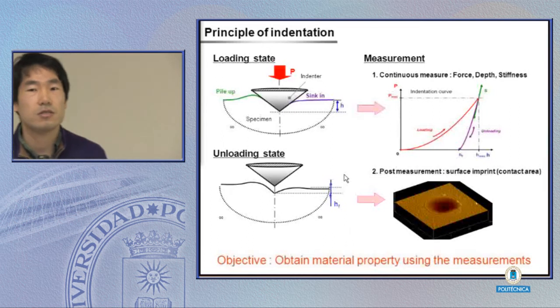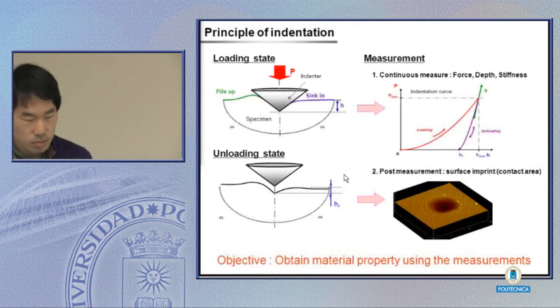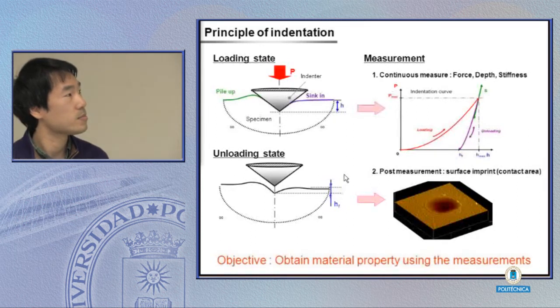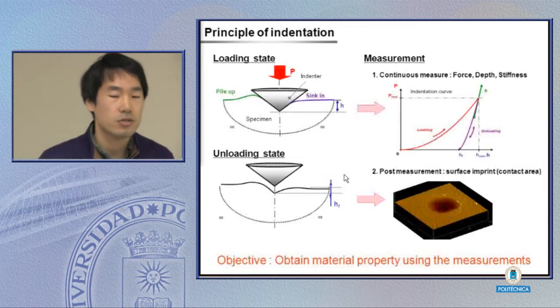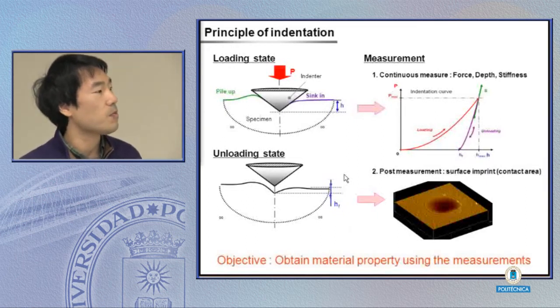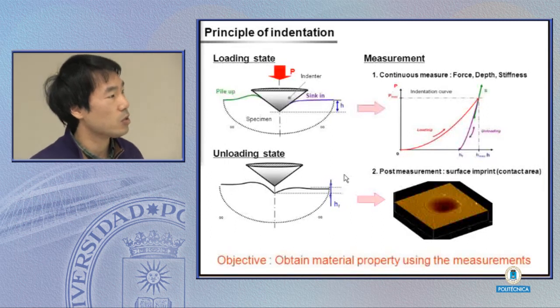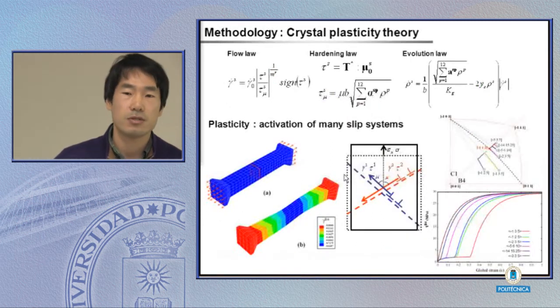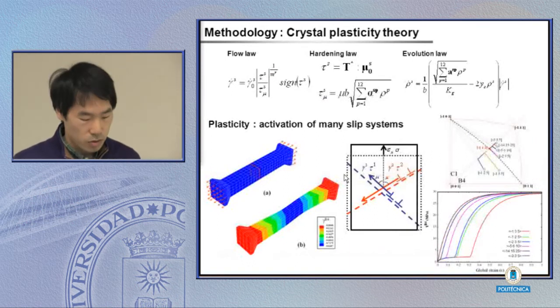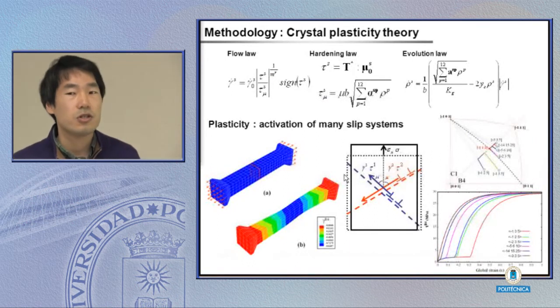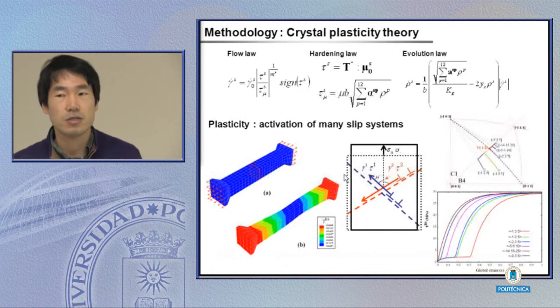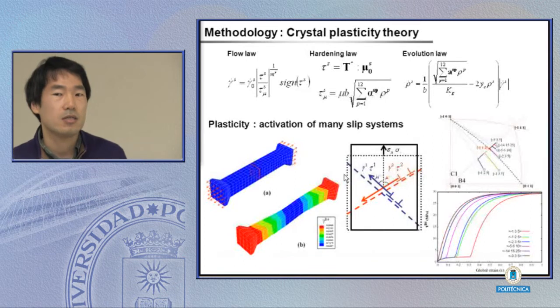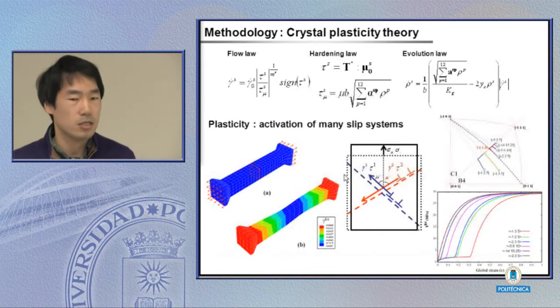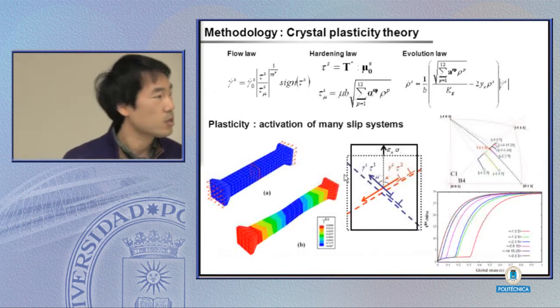Now, let's scale down to the microscale simulation, such as nano-indentation. The objective of nano-indentation is to get the material properties using the load displacement curve and surface imprint. So this nano-indentation procedure can be simulated by FEM simulation or crystal plasticity. And this kind of simulation is supporting the experimental result and confirming the experimental test.